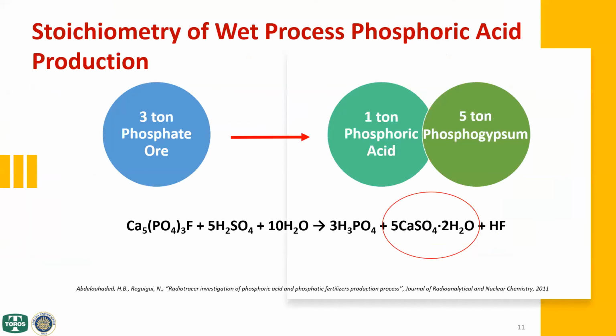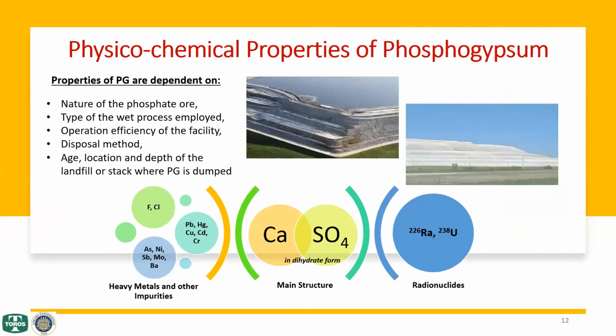According to the stoichiometry of the reaction, 5 tons of phosphogypsum is generated per ton of phosphoric acid. So the generation of the byproduct is higher than the desired product. Phosphogypsum is mainly composed of gypsum dihydrate, also containing unreacted phosphate rock and minor solid phases of reaction residues such as calcium oxide, sulfates, silicon dioxide, aluminum oxide, and fluorides.